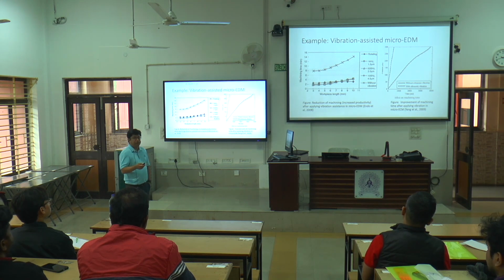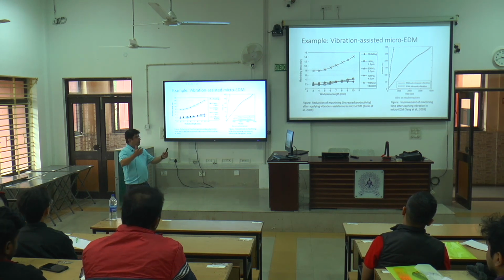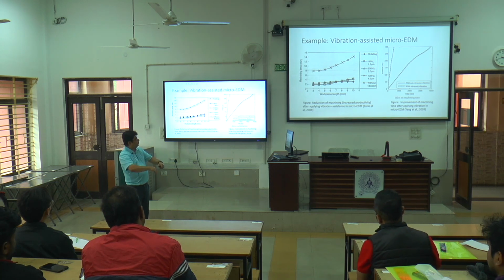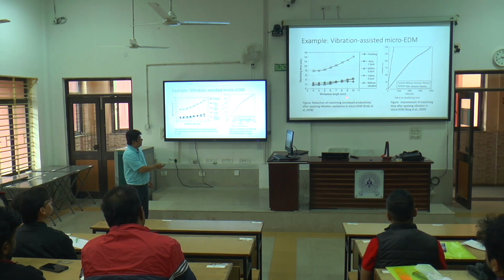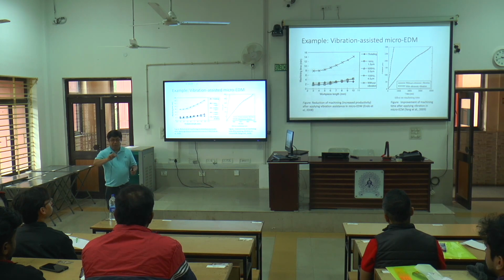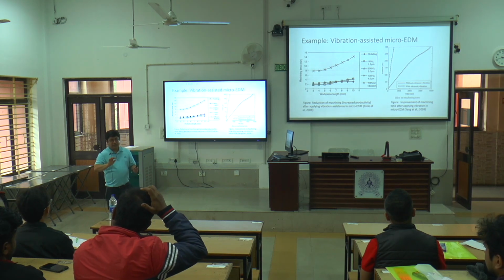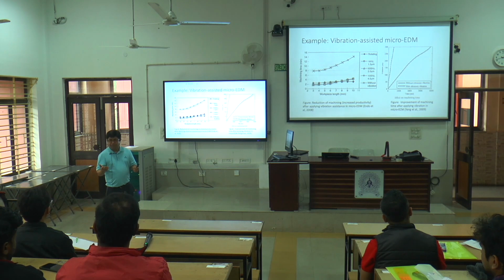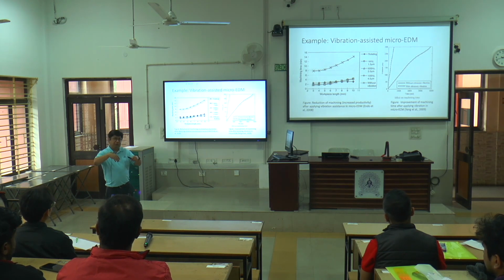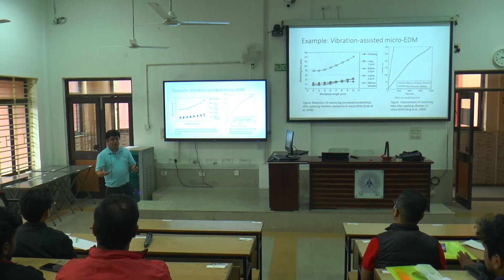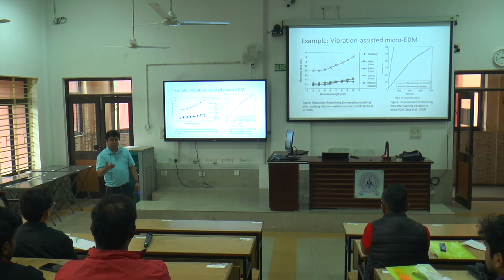But usually the reasons are when you are going deeper. If you are making holes in a very thin part, you do not see the effect that much. But when you are machining high aspect ratio holes, like for example more than 20, maybe 50, or around that, you see that after some time machining becomes unstable. It's not going anywhere, right? Then you need some further assistance to flush debris away from the machining zone.